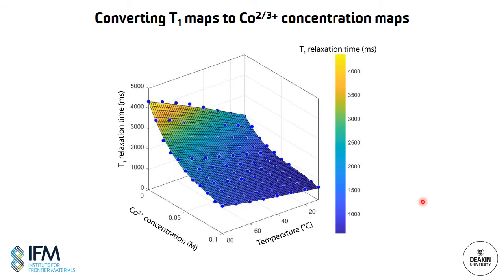We can then use calibration measurements to determine an empirical formula for T1 as a function of both the sample temperature and the concentration of the paramagnetic cobalt species. And this surface then allows us to convert the measured T1 for each pixel into a cobalt 2+ concentration using the known temperature for that pixel.